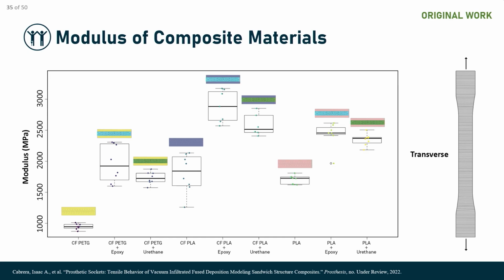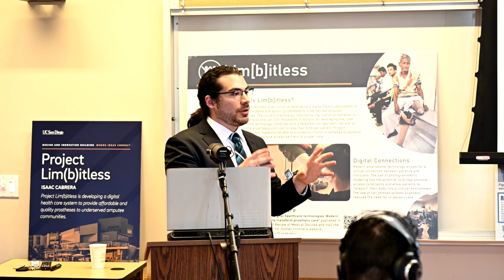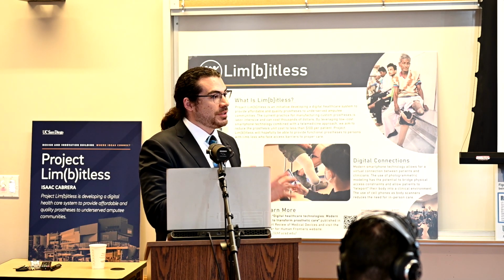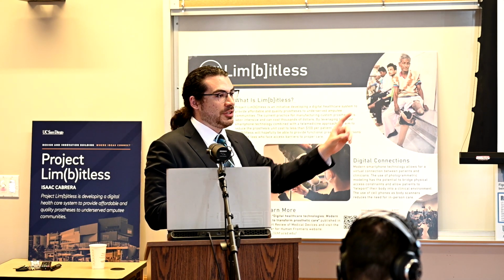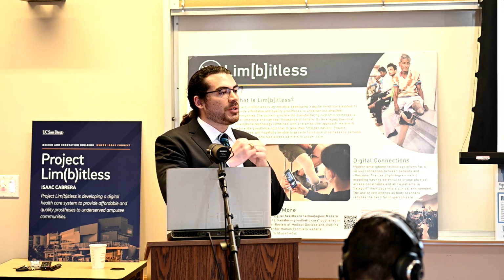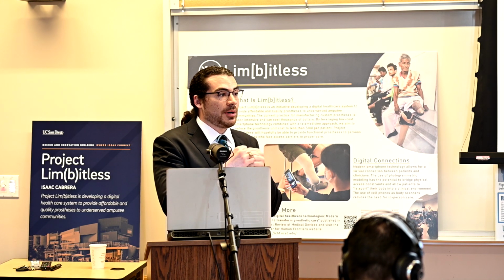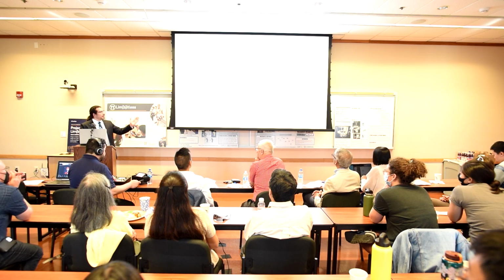Something that I didn't mention before is that our materials, our filaments and our resins, were compliance matched for stiffness. And so what you're seeing here is that they're much weaker and much less stiff due to the printing process itself. But by creating the composites, we're able to regain a lot of that stiffness and reduce that anisotropy.